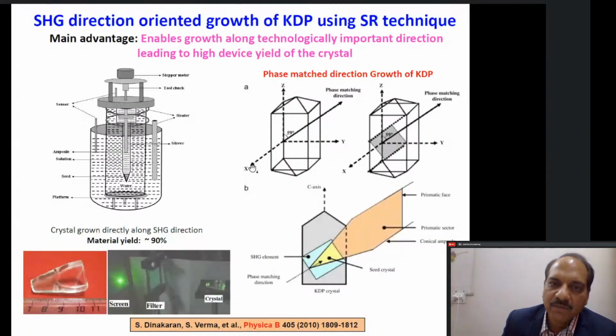So we first cut this crystal at 59 degrees to the Z axis, and then we make two normal cuts along this 59 degrees direction. Finally, we get an element, the shaded portion only, which is the only device element possible from a crystal of this big size. The usable volume when you grow a crystal in conventional morphology is only around 20-25%. That is, a maximum of 75% of its volume goes to waste. That's a huge loss, I would say, for a material scientist.